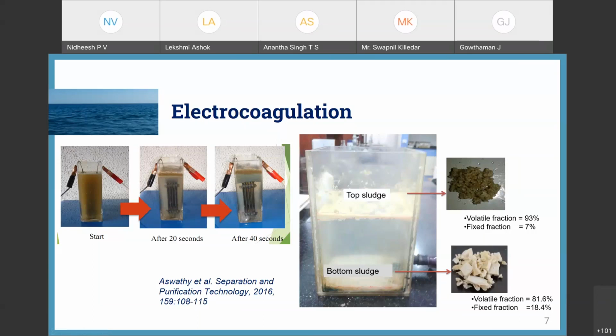That is why, in our normal procedure, we keep the muffle furnace at 600 degrees Celsius for 20 minutes, and a normal oven at 100 degrees. By this normal procedure, we find out the organic and inorganic fraction. You can see that the top portion contains 93% organic content, with a very small inorganic fraction. But here, you can see it contains a higher amount of inorganic content compared to the top sludge.